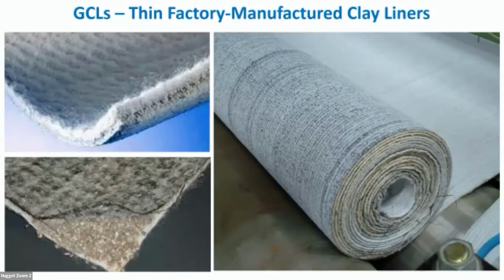What are GCLs, or geosynthetic clay liners, these thin factory manufactured clay liners? Essentially they look like a carpet. We've got two geotextiles sandwiching between them about 4 to 5 kilograms per meter square of granular bentonite. And that's the granular bentonite here. The geotextiles are non-woven on the top. It's got a woven on the bottom here.